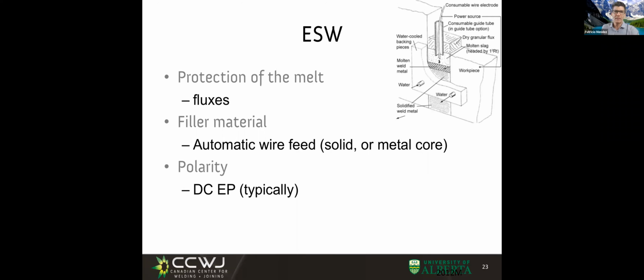Okay, how do we protect the melt in this case? Fluxes, while before it used to be gas for electrogas. The filler material is automated wire feed, can be solid or can be metal core. And this matters. When you're welding something with a consumable that is more or less the same, which we call homogeneous weld, still it is not exactly the same, because the plate was rolled and maybe even heat treated, and has very different properties than the microstructure of the weld that was molten metal that went solid and nobody ever rolled it. How do you make this cast structure of a weld have as good properties as rolled material? Not trivial.